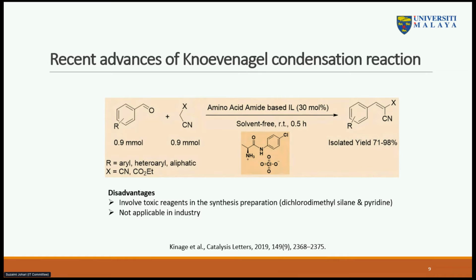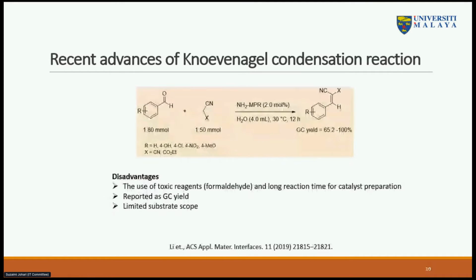And this kind of catalyst, although it showed quite satisfying results, and it's isolated, not in gas chromatography here, but still it's not applicable in industry or in large scale. And the last one is the type of polymeric mesoporous-based catalyst, also used in previous work. However, again, the use of toxic reagents, for example formaldehyde, and a very long reaction time for the catalyst preparation is the disadvantage of this work. And also, as we can see, the yield is reported as gas chromatography, not as an isolated yield. And again, the limitation of the substrate scope used in this Knoevenagel condensation reaction.